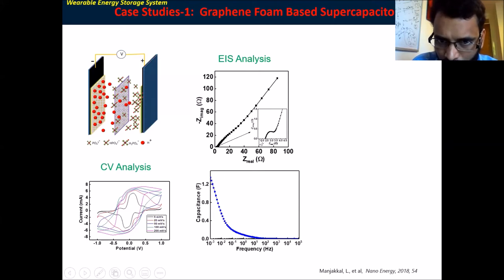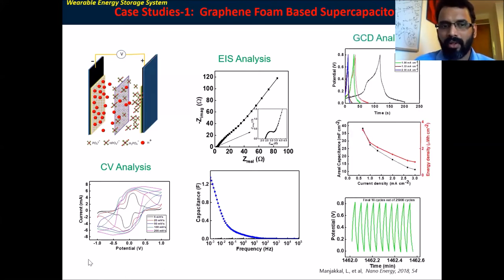As you can see here, in the impedance spectroscopic analysis, in the inset, from 0 to 2.5 the solution resistance is very minor, we can say negligible. And the charge transfer semicircle is again about 1 ohm, so ions can easily diffuse into the surface of the electrode and easily absorb on the surface. From the different frequency range, the capacitance started from 1.2 farad at low frequency. And here you can see the charging discharging analysis, depending on this material.